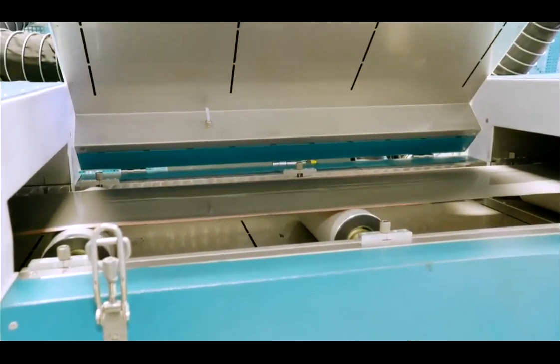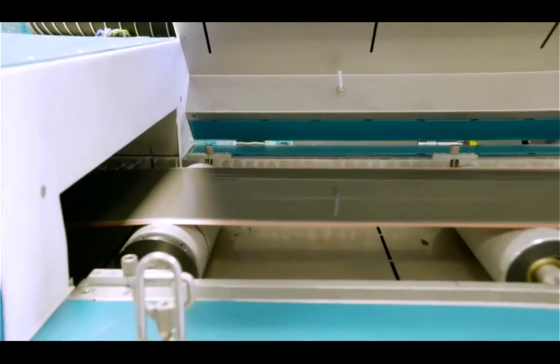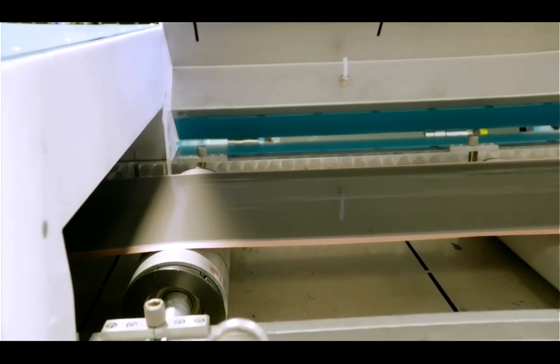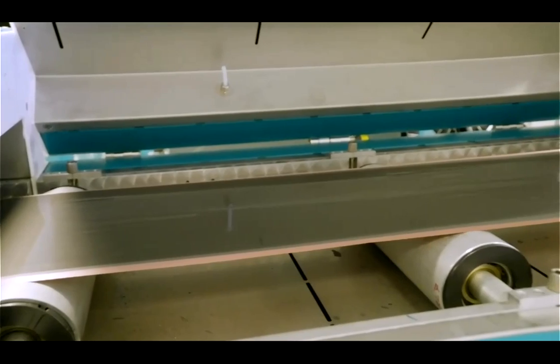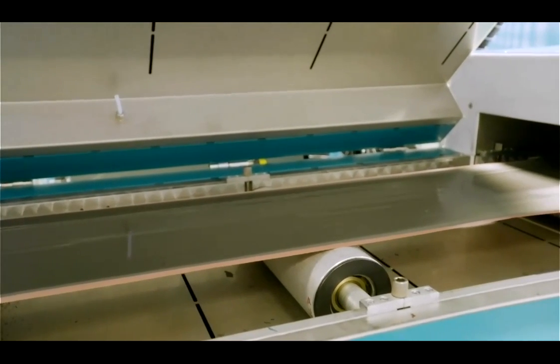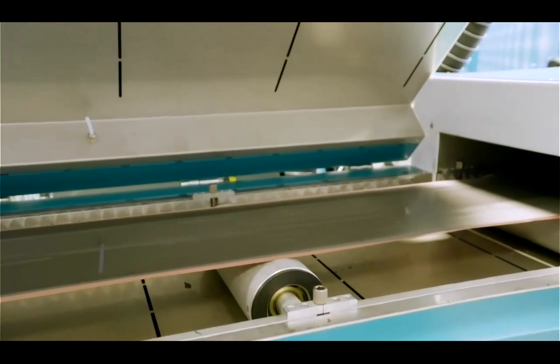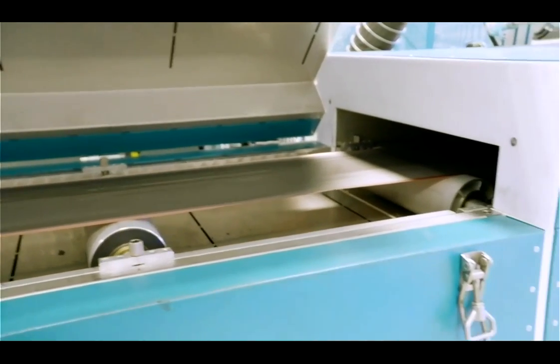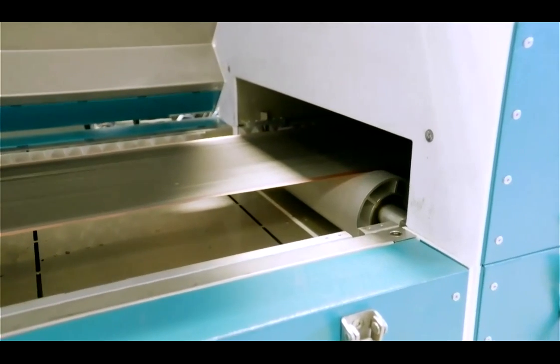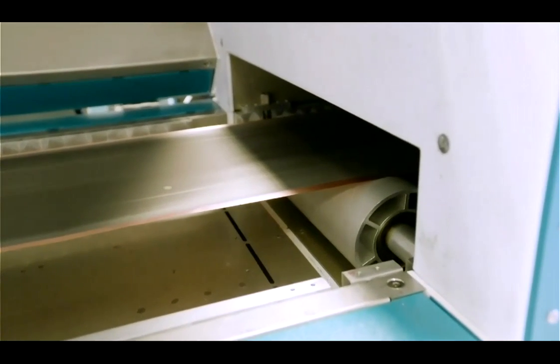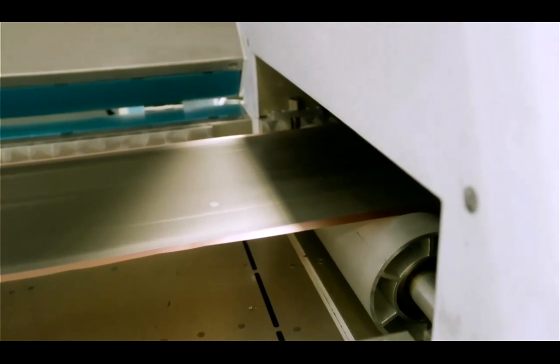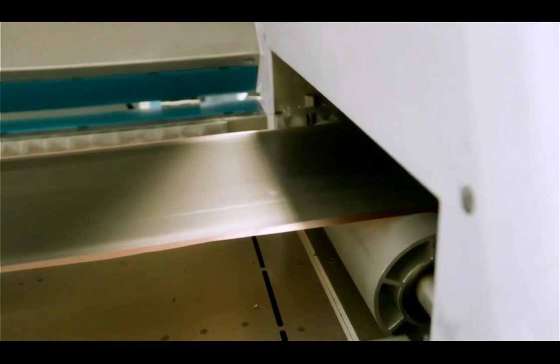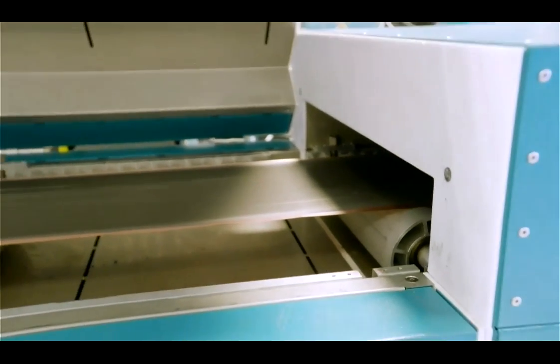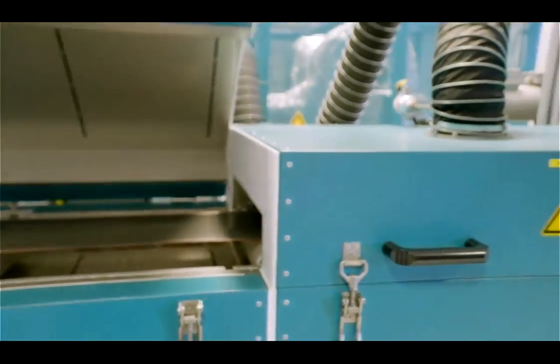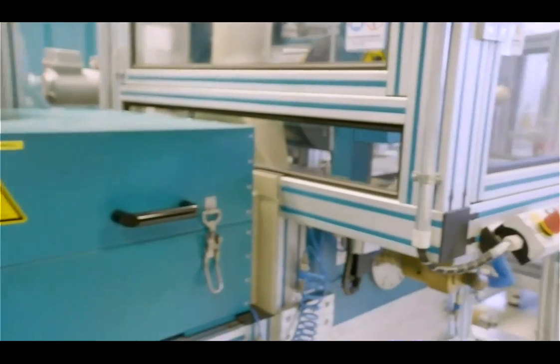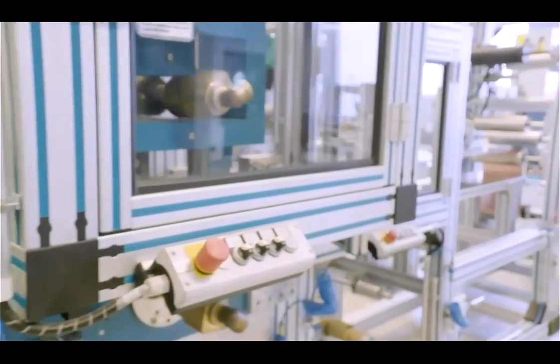Okay, this step is a very important step. Some people don't pay attention to this process, but it's really important because here we are fixing the microstructure of the electrode. If the temperature we are using for drying is too high, for example, we will provoke the migration of the binder towards the surface. If the temperature is too low, the opposite will occur, and the binder will migrate towards the current collector. Okay, so it is very, very important to fix the temperature profiles in the oven.